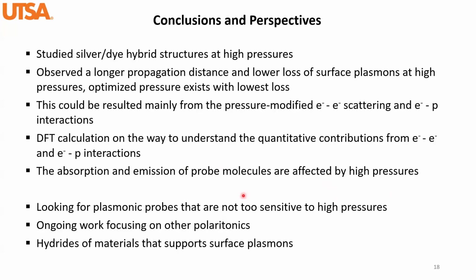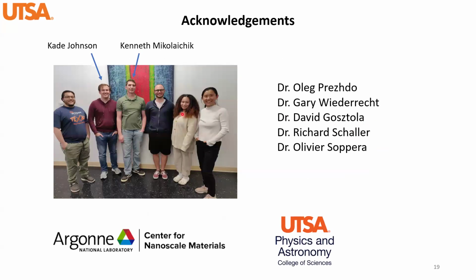And so that's why we're looking at this moment for plasmonic probes that are not too sensitive to high pressures. And we have been thinking about NV centers for a while. And we need to discuss that more in detail with Ross and Steve, maybe. And also, we have ongoing work focusing on other polaritons, by which we mean phonon polaritons and exciton polaritons. That is similar to surface plasmon polaritons. They are just phonon vibration and exciton vibration propagating along the surface. And also, we are interested in looking at hydrides of materials that can support surface plasmons to find a better chance of plasmon propagation. And that is all I want to talk about for my current research.